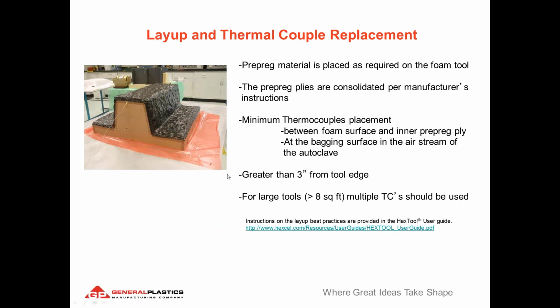The layup and thermocouple placement is really important as well. Typically on a metallic tool, you would have your thermocouple placement somewhere in the middle of your ply layups, because you'd be heating from both sides. On a foam tool, you want to have your lagging thermocouple between your foam surface and the lower ply of your composite, because you're only heating from the oven surface, which is above the tool, through the top of the graphite. So you want to make sure your second thermocouple, which is your leading thermocouple, is on top of the bag, and then make sure those two match up to show that you've cured the resin out as directed by the supplier.